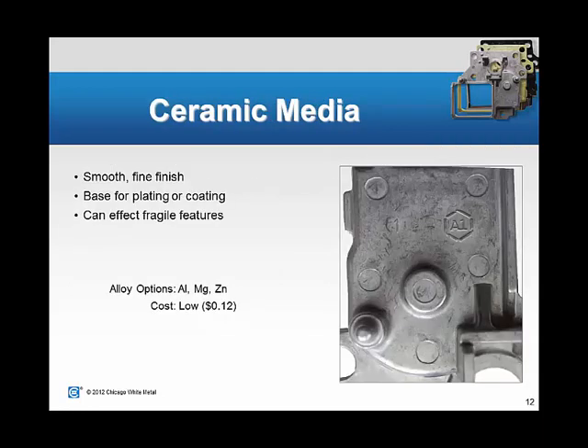Ceramic media. This is a vibratory deburr process where parts are put in bulk into a tub or a large bowl and then vibrated. The interaction between the media and the part is what creates the surface. The ceramic provides a smooth, fine finish. Again, it's a very good base for plating or coatings that come later. And the ceramic, just like the previous slide, can be aggressive to fragile features, so it's something to keep in mind. This can be done with all 3 alloy types, aluminum, mag, and zinc, at about a 12-cent cost.